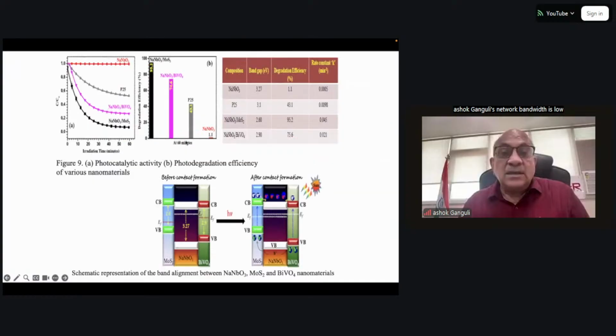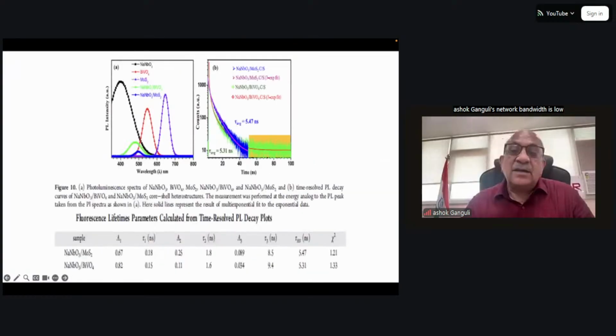This is another method to explain that lifetime measurements tell you how stable your species is. So if you have longer lifetimes, that means the species is more stable, and you can measure these fluorescence lifetimes. You can study the PL intensities. Smaller the PL intensity, it means the lifetime is more. That means electron and hole are not recombining to give you light. So photoluminescence should be low. And so the blue plot, which is this sodium niobate molybdenum sulfide, is the best among all these materials in terms of the lower photoluminescence, which means longer lifetimes of electrons and holes.